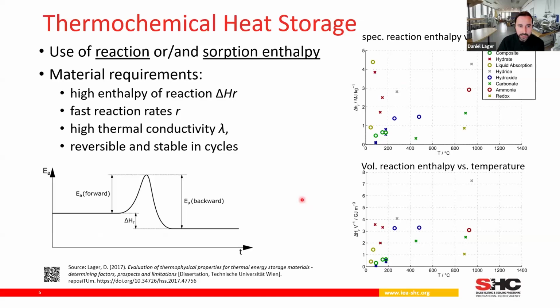Last but not least, thermochemical materials. So here you want to have a high enthalpy of the reaction or a high sorption enthalpy, depends on the material you're looking at. You want to have fast reaction rates, high thermal conductivity again for charging and discharging power. And this is the important point: the reaction must be reversible and stable for the application, with the number of cycles you need in the end.